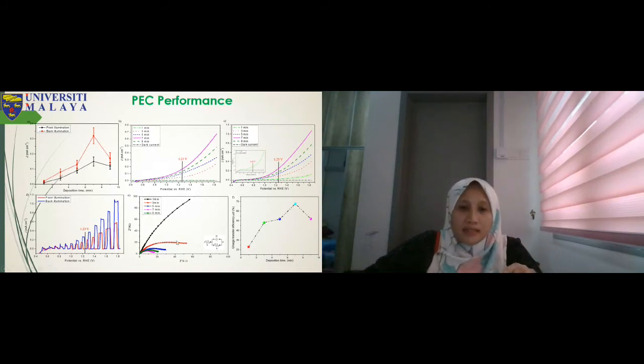So this one is the resistance for the PEC. We need a low charge transfer resistance here because lower charge transfer means lower resistance between the electrolyte and the photoelectrode. It can be observed that the 7 minutes deposition time has the lowest charge transfer resistance.